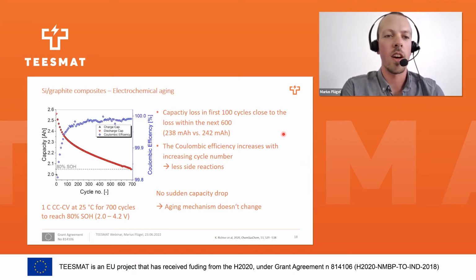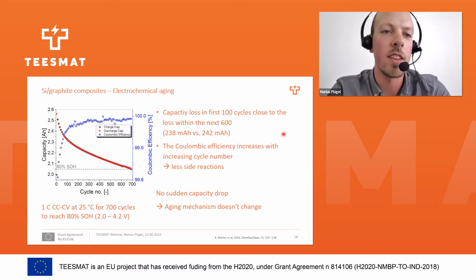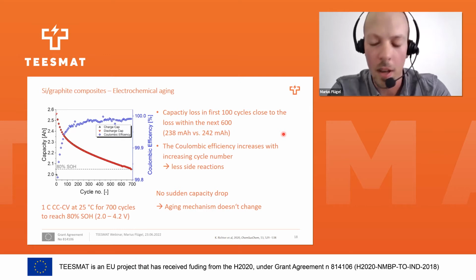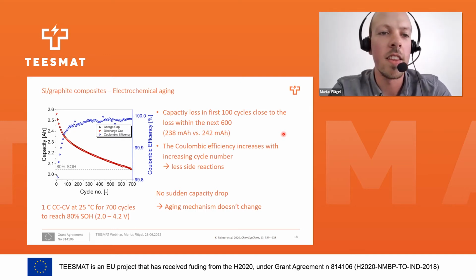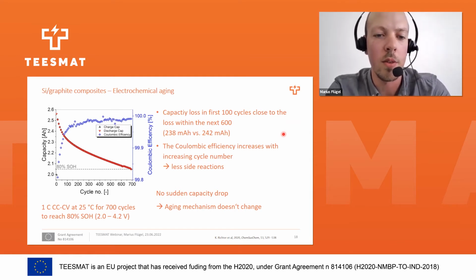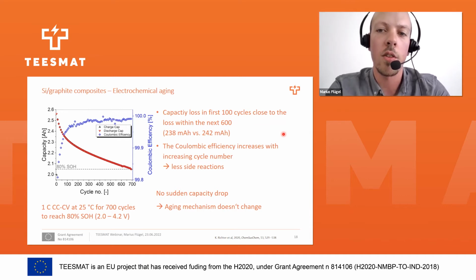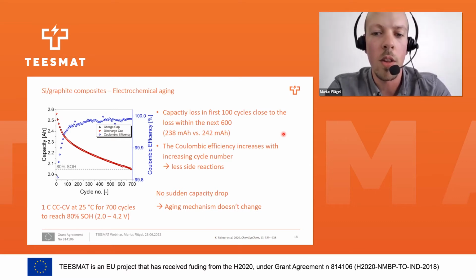For state-of-the-art anodes, silicon is added as a material with a high specific energy, high specific capacity, and therefore we also investigated the aging processes of silicon graphite composites. Those cells were aged at room temperature for 700 cycles until they reached 80% of SOH. And the capacity loss within the first 100 cycles was close to the capacity loss within the next 600 cycles. However, we did not see a sudden capacity drop, so the aging mechanism doesn't change over the cycling.